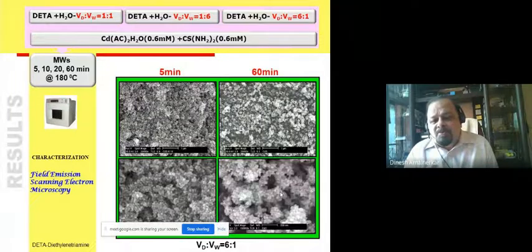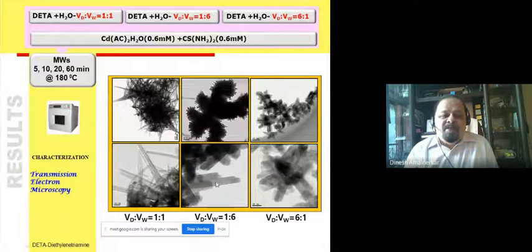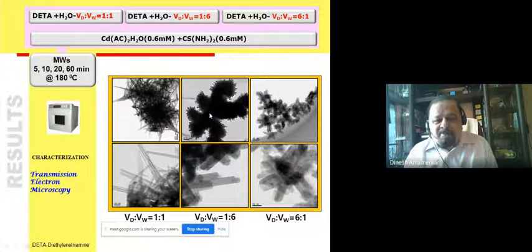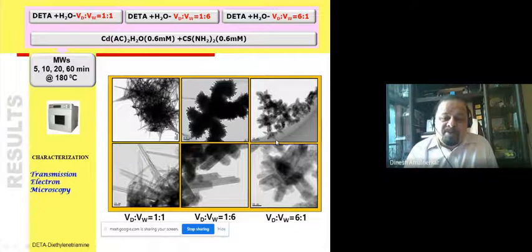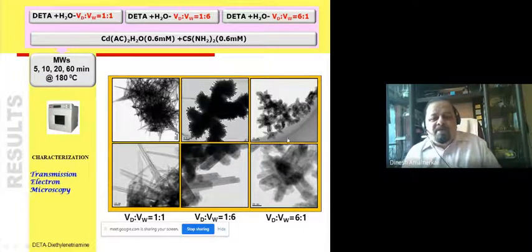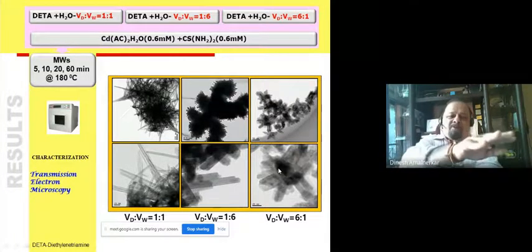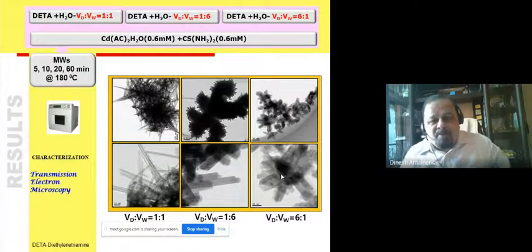Now, this doesn't apparently show the hierarchical nanostructure for this particular ratio, but when we took the FETEM, the results were much more clear. For this particular volume ratio, 1:1, we can see a nano cobweb kind of morphology, and nanorods can be clearly seen. For the 1:6 volume to volume ratio, we can find maybe a nano buoy kind of morphology, and the rods and the faceted growth can be clearly seen here. Most importantly, when we used DETA and deionized water in a 6:1 ratio, we can see this kind of floral pattern. Please remember, we observed this way back in 2007 using normal FETEM with no more advanced features associated with that. But still, we could get a beautiful floral structure. This is one rod, plus another, then on top of that there is another rod, and we get a floral pattern. That is what we interpreted.